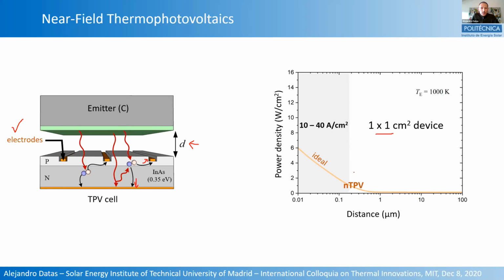Well, if you do the simulation of this device, you can get this curve here for the power density that increases substantially when you go below 1 micron distance, and then up to 6 watts per square centimeter. But you have to pay attention to the current density, because we are using in this case a very low bandgap cell of 0.35 electron volts, which is needed to tackle the spectrum of the emitter, which in this case is 1000 Kelvin. So you need very low bandgap cells. And then you will have huge current densities to produce these powers, in the range of 10 to 40 amperes per square centimeter. And this is, of course, very challenging regarding the electrodes.